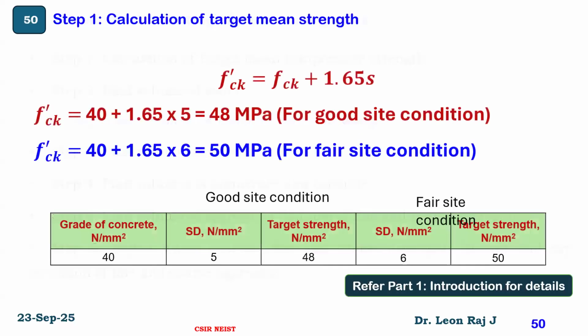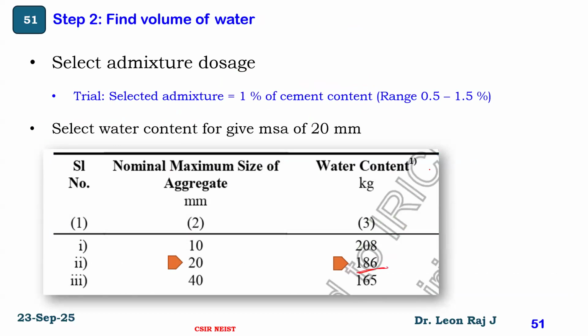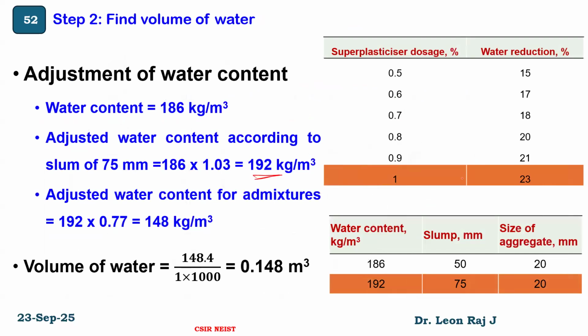So this is the M40 grade. So 40 plus, this is the standard deviation, 5, gives 48 as the target strength for good site condition. Then select the water content. Water content is selected as 186, and this needs to be corrected for slump value and admixture dosage. For slump value, it is corrected to 192 kilogram per meter cube. Then for admixture dosage, it is corrected to 148. So it needs to be corrected for two reasons: number one is slump value, and number two is admixture dosage.